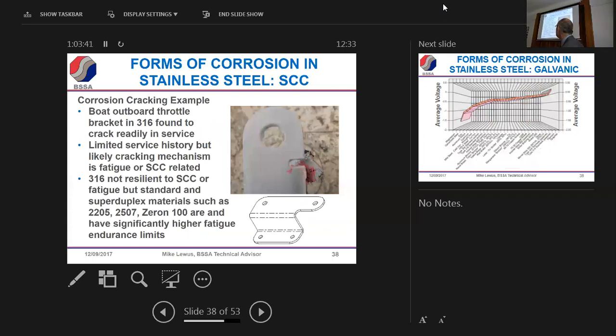This was an interesting one because it came from the Lifeboat Association. They got this bracket that was supporting an outboard motor. It's a prototype bracket. They'd only used it a few times, and they kept getting it cracking. And you can see where they've done some dye penetrant testing, looking at whether there's any cracks at the surface. You can see signs of cracks there, and it actually is at this corner here.